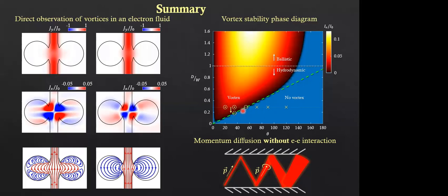It's about 150 nanometer, and from there we can calculate the momentum relaxing and momentum conserving mean free path, because one of them we get directly from transport. The momentum relaxing mean free path we get from bulk transport to about 20 micron, and from there we get our momentum conserving mean free path to be very small.